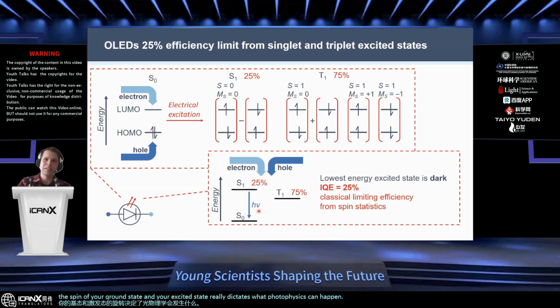And in our case, if we were interested in making a light emitting material, we try to match up the spin of your ground and your excited state so that you get more efficient radiative transitions. And for molecules with a singlet ground state, because you form this singlet exciton 25% of the time, you have to put some work in to get the 75% triplet excitons to work for you.